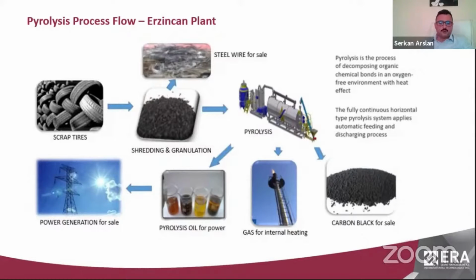Then the tires are shredded into small parts. The PSD, particle size distribution of granules, is very important. Smaller particles means more surface area and more efficient pyrolysis process. And the thick steel wires from the OTRs are removed from the tires and can be sold. Also, we have thin wires from car tires and truck tires, and these are removed before the inlet of the pyrolysis reactor with magnet separators, but it is a little bit contaminated with textiles. The textiles should be removed so that we can sell this steel, because the textile is a contamination, a part of the tire.